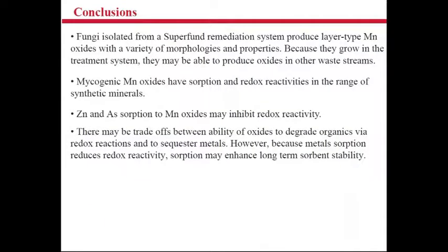Okay. So to sum up and finish off, as my job as opening act here today, I want to drive home a few points. Fungi isolated from the Superfund site produce layer-type oxides, and there's a whole variety of different, subtly different oxide structures that we seem to be able to produce. Because they can exist in these waste treatment streams, they may be useful in designing remediation systems where we can incorporate them into a treatment.